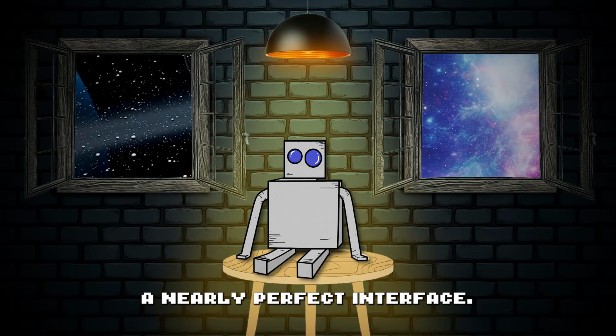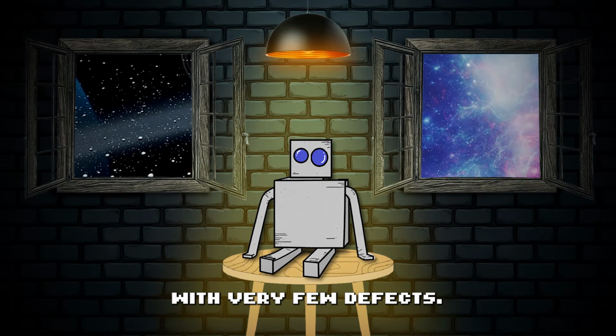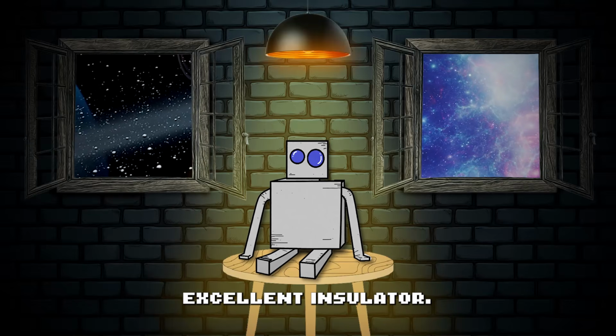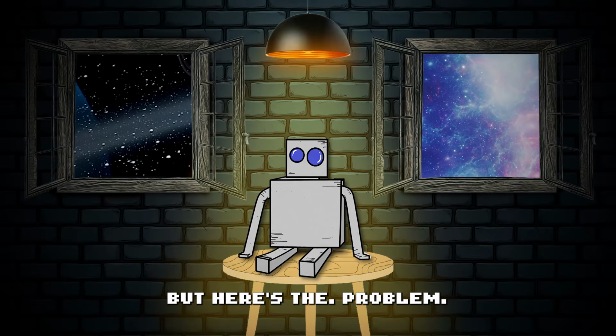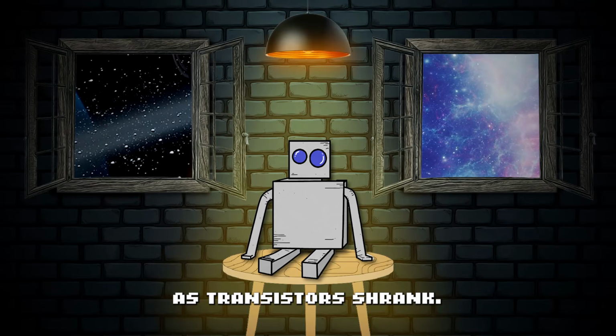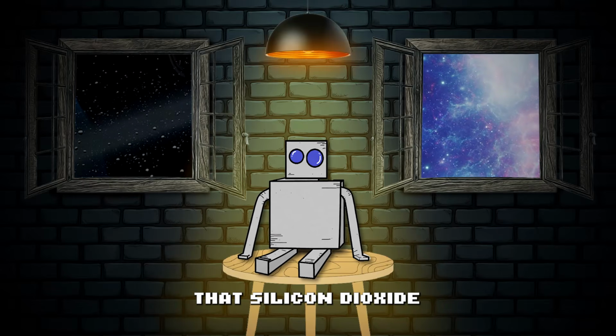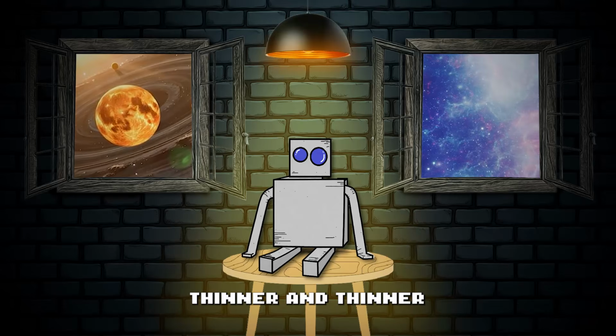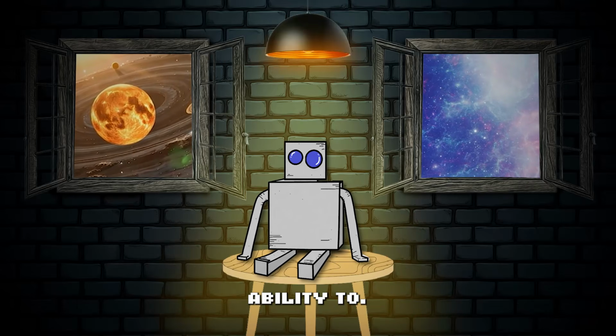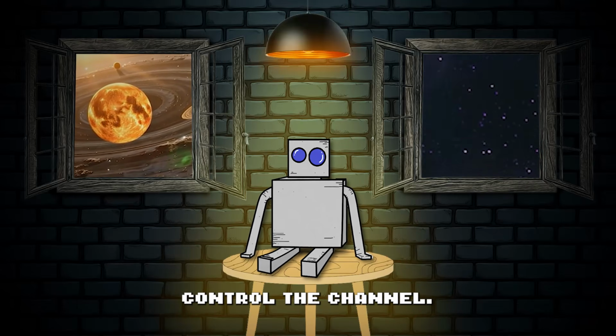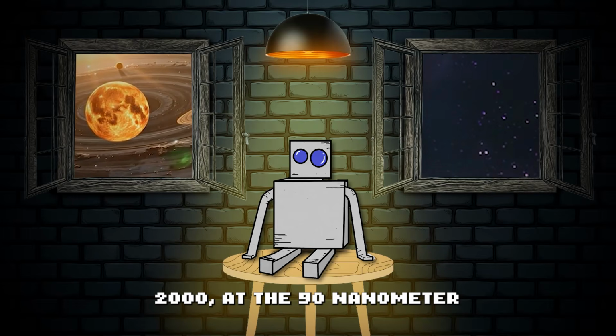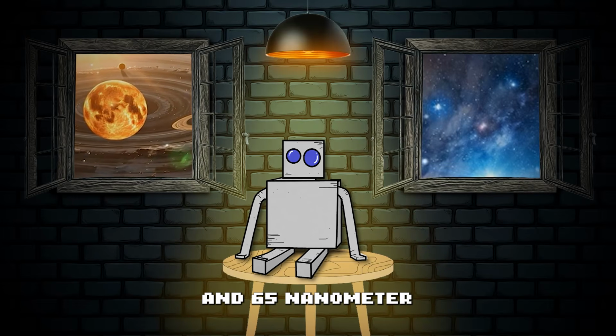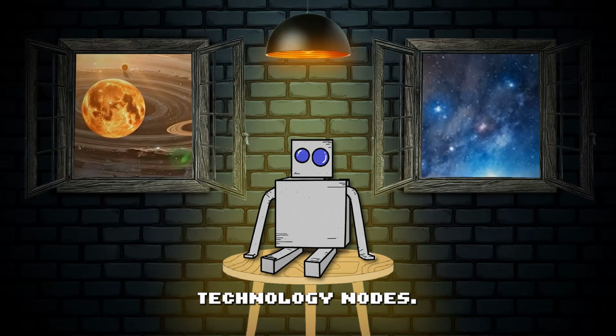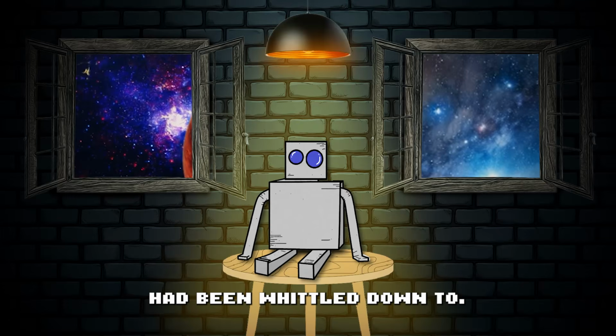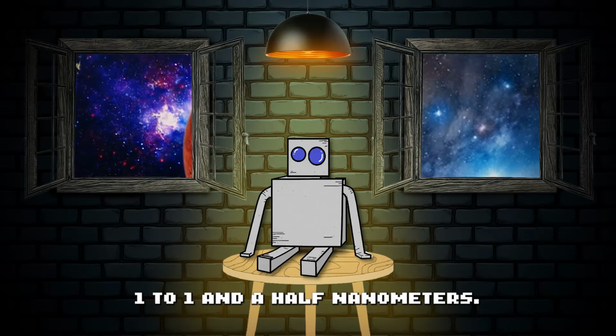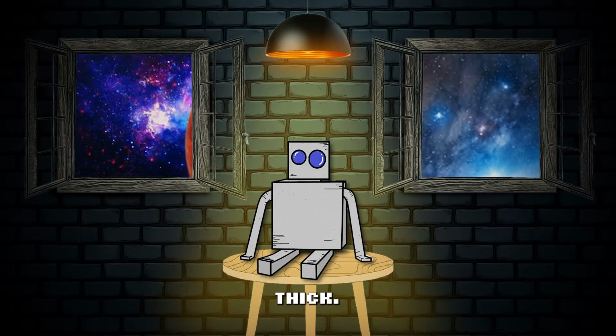It worked beautifully because silicon dioxide is easy to grow on silicon. It forms a nearly perfect interface with very few defects, and it's an excellent insulator. But here's the problem. As transistors shrank, that silicon dioxide layer had to get thinner and thinner to maintain the gate's ability to control the channel. By the early 2000s, at the 90 nanometer and 65 nanometer technology nodes, the gate oxide had been whittled down to just about 1 to 1.5 nanometers thick.